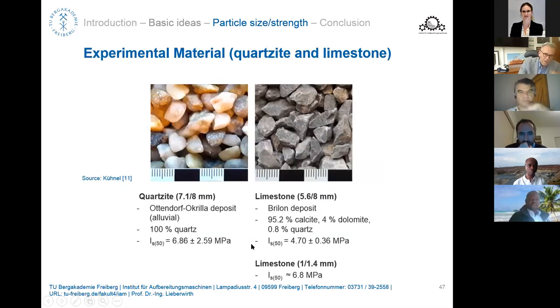And we repeated the tests with a similar approach with natural material, with quartzite and limestone, to have also a comparison to the old Fürstenau investigations. So we used here a quartzite, also in a narrow fraction, 7.1 to 8 millimeters, and the limestone in various particle sizes, 5.6 to 8 millimeters and 1 to 1.4 millimeters. Here, the 1 to 1.4 millimeters exhibited very similar strengths compared to this quartzite, 7 to 8 millimeters, slightly less than the 6.8 megapascal.